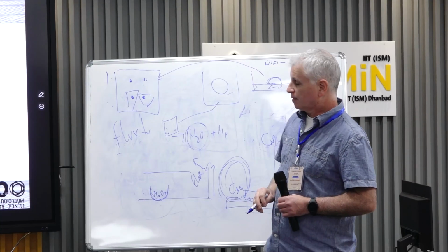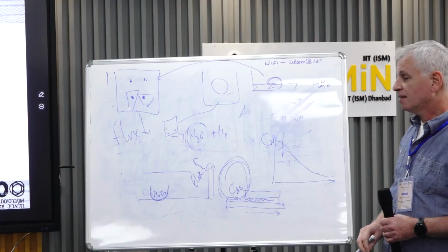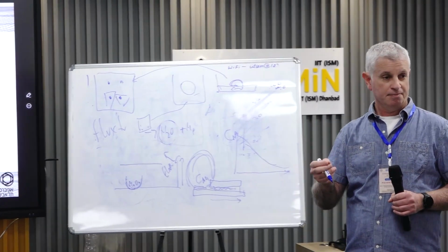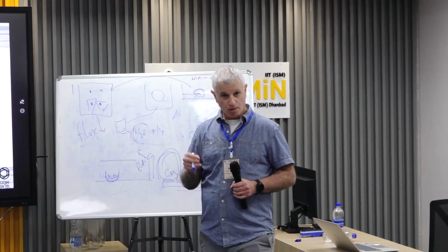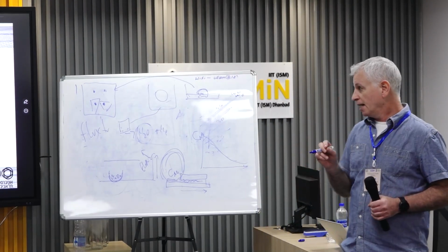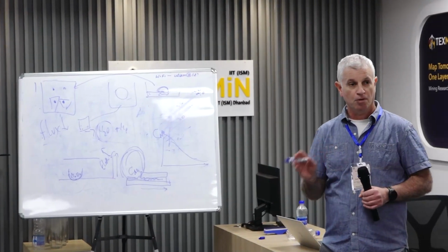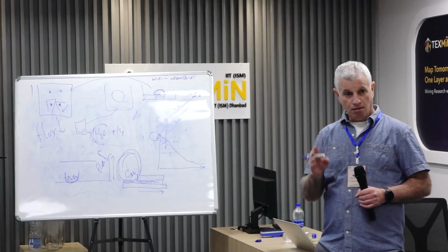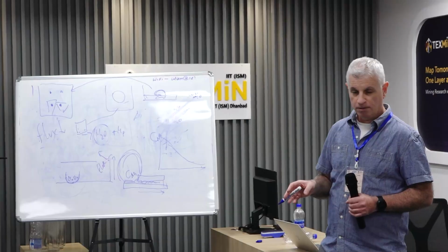But one thing that we didn't take into account is the interaction of the metal seed with the TMD. In our case, we use gold, for several reasons. We know that gold has no solubility of sulfur or molybdenum. We know that sulfur has a very strong bonding to gold.